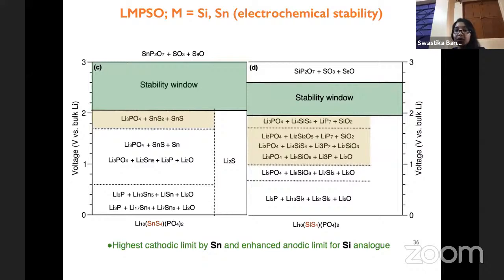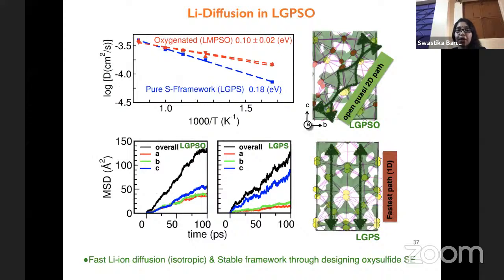which electrode is in use, because the usability of the electrolyte depends on the chemical potential at which the electrode operates. So we need to choose the electrolyte in a smarter way after keeping in mind what the potential electrodes are. So we find the highest cathodic limit can be obtained by tin, and enhanced anodic limit can be obtained by silicon. Now I again show you the lithium diffusion properties for the LGPSO. So far, what we were expecting is that we'll design something which will be more stable, but it will not sacrifice the diffusion. So we really found that this LMPSO.